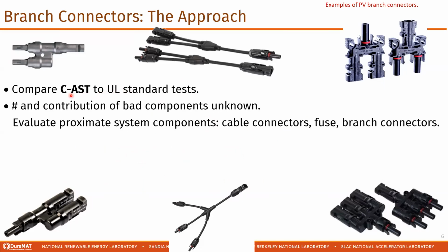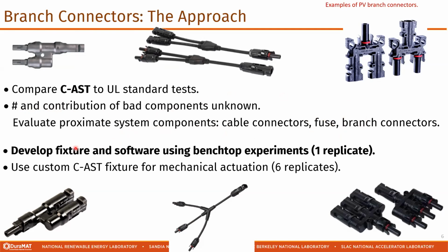And then the approach here, we want to compare CAST, which I'm talking about today, to the UL standard tests. This is something that Mike Kempe is looking into. We approached it in CAST with the philosophy that the number and contribution of the bad components was not known. So we considered all of the adjoining system components as a sample assembly. That includes the cable connectors that go to the branch connector, a discrete fuse, and then also the branch connectors themselves. I'll focus today on developing the fixture and the software using benchtop experiments. We're presently in the process of incorporating this into CAST using the dedicated fixture to examine multiple replicates at the same time.